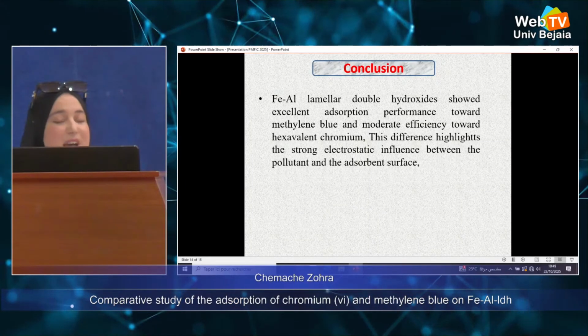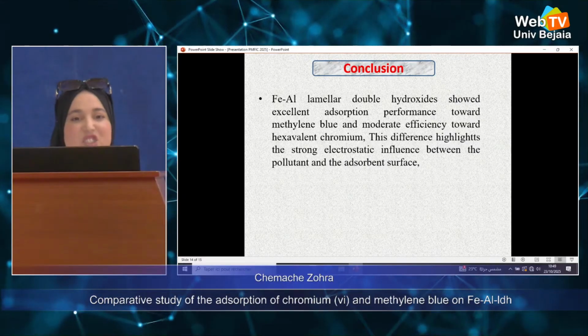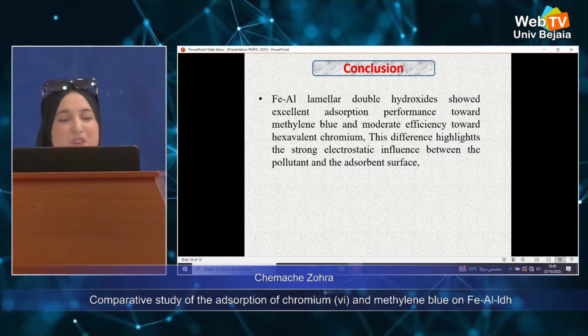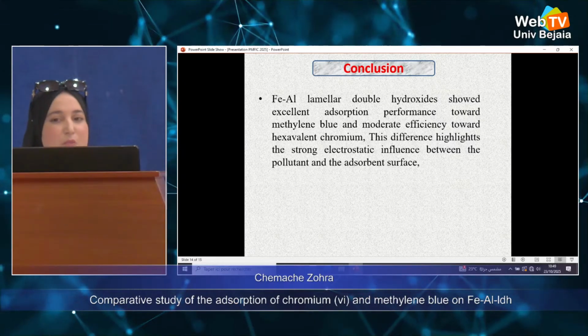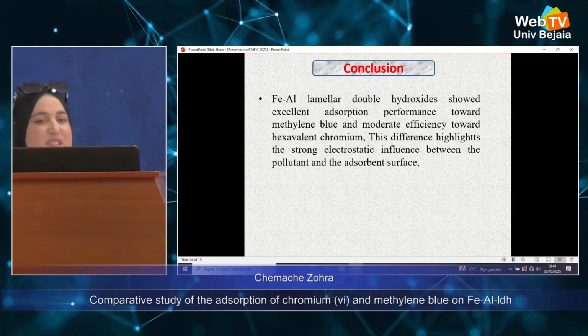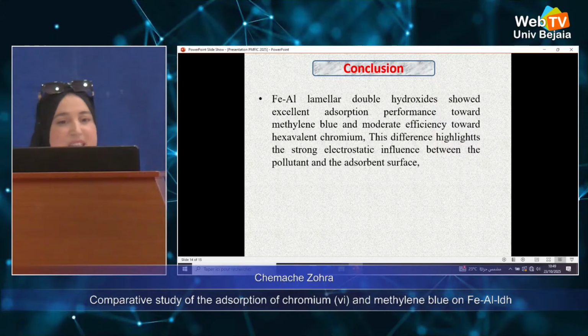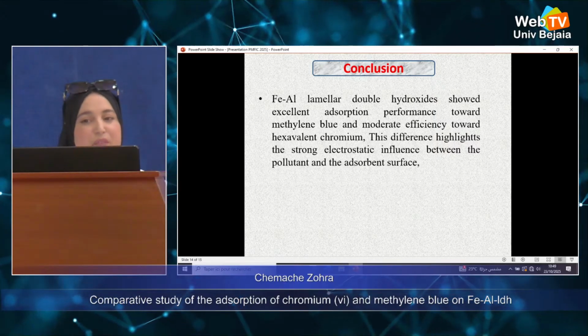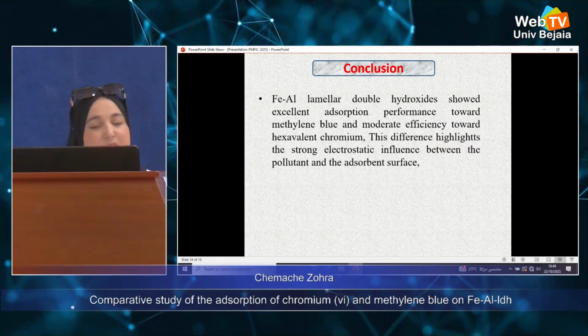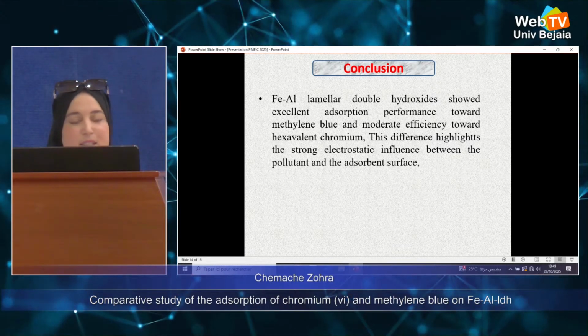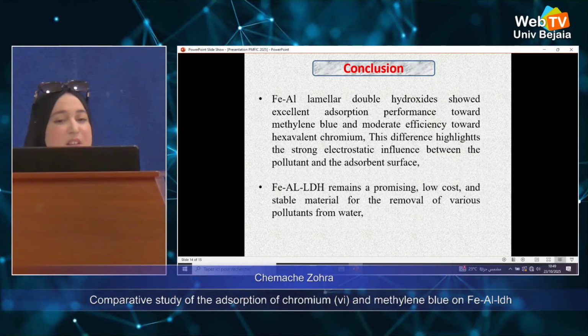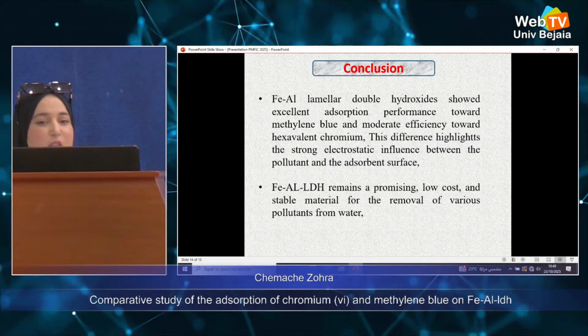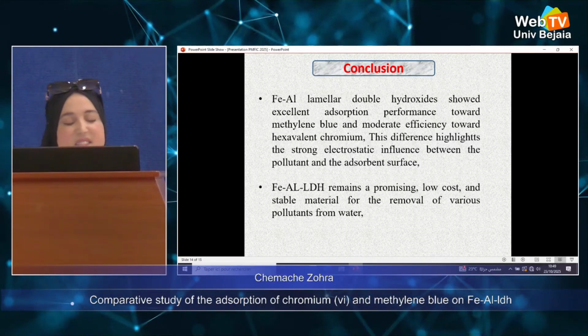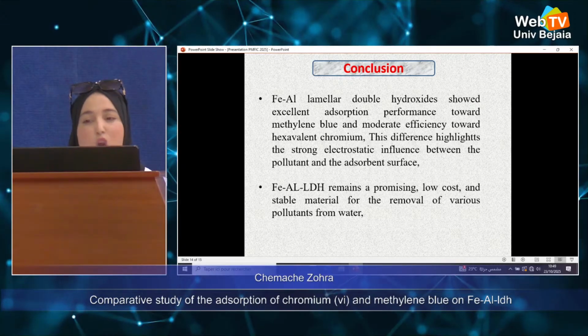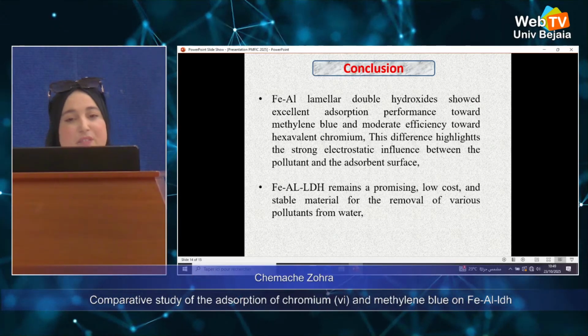In conclusion, iron aluminium lamellar double hydroxides showed excellent adsorption performance toward methylene blue and moderate efficiency toward hexavalent chromium. This difference highlights the strong electrostatic influence between the pollutant and the adsorbent surface. Iron aluminium LDH remains a promising, low-cost and stable material for the removal of various pollutants from water.